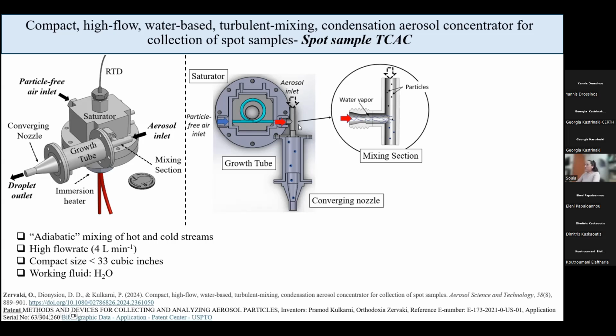And we have a theoretically instant adiabatic mixing of these two streams that causes generation of supersaturation, where the water vapor condenses on the surface of the particulates. Then we have the droplet formation and growth that is further enhanced in the growth tube, where more time and space is given for the mixed flow and the droplet growth to happen.